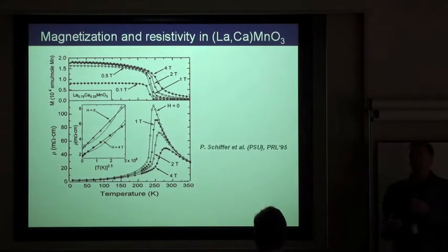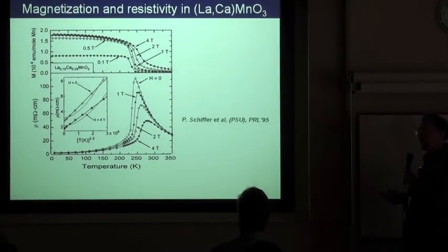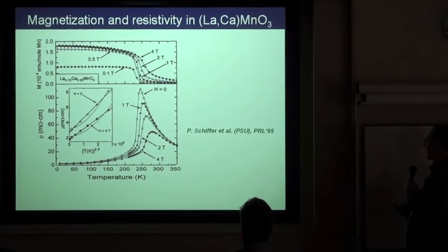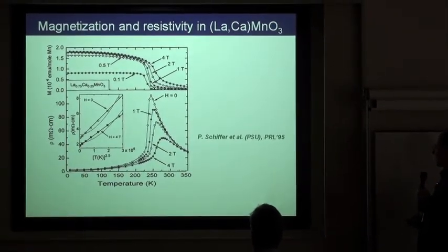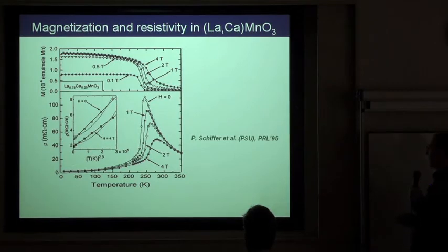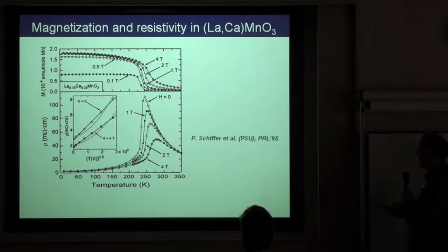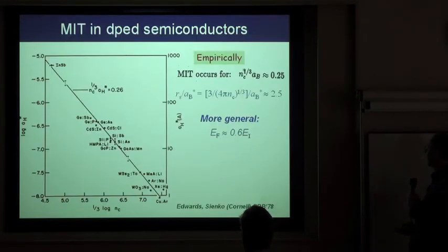And actually this is well known from colossal negative magnetoresistance systems like manganites, that application of the magnetic field orders the phase at low temperature and makes the resistance lower, whereas near the phase transition, which means disorder, when disorder causes localization, there is stronger resistance.